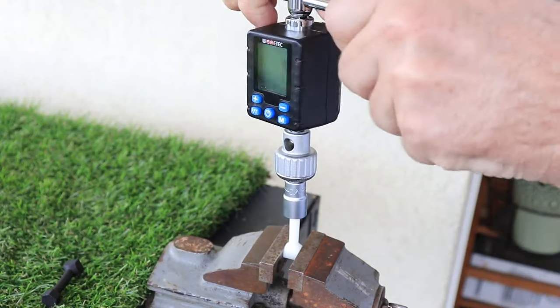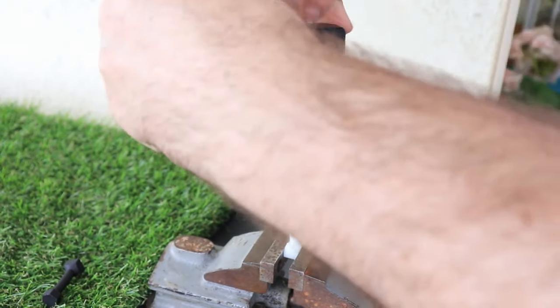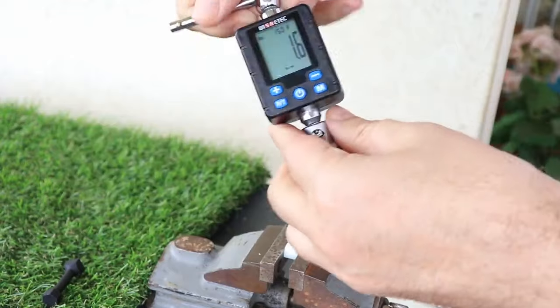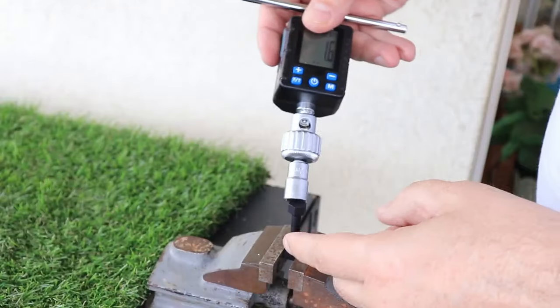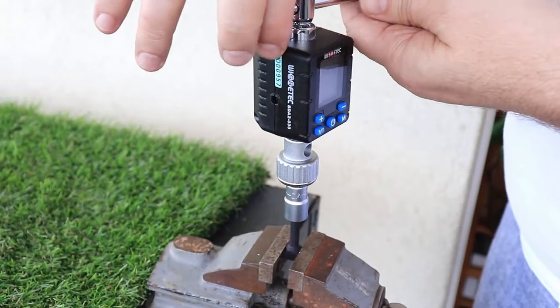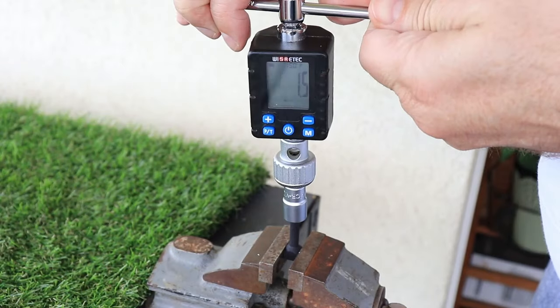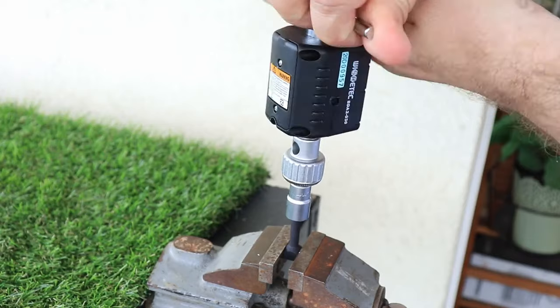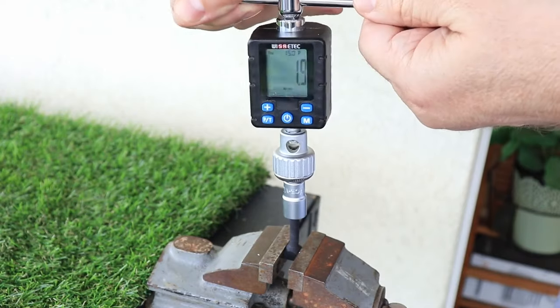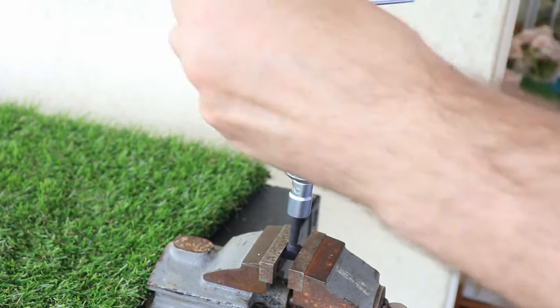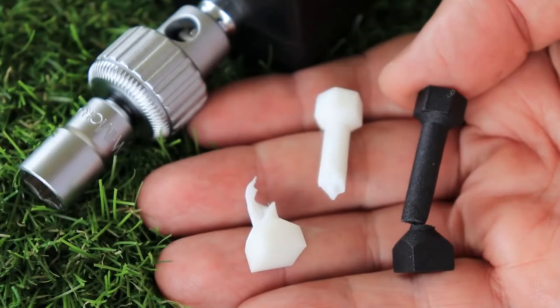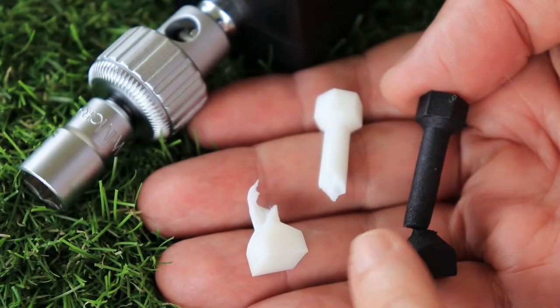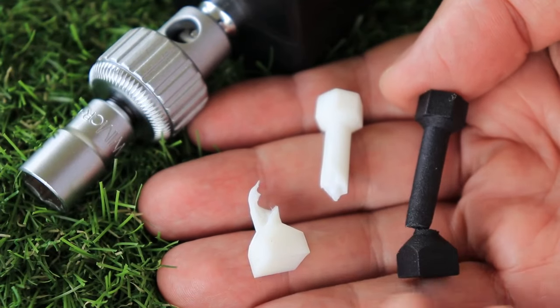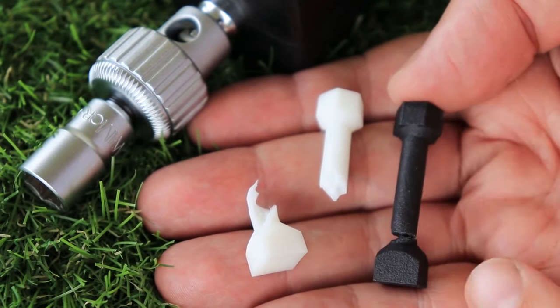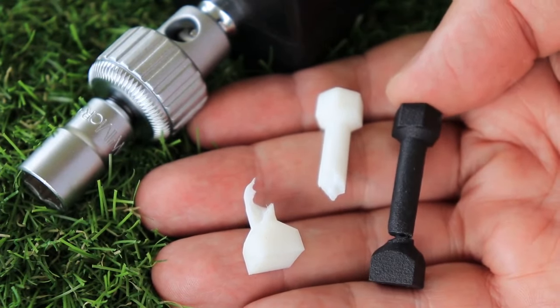1.5. 1.6 was the peak. Nylon. 1.5. 1.9. Oops. And as I predicted, the resin broke very suddenly. I got these very sharp edges here, and I could actually feel where the nylon will fail slowly.